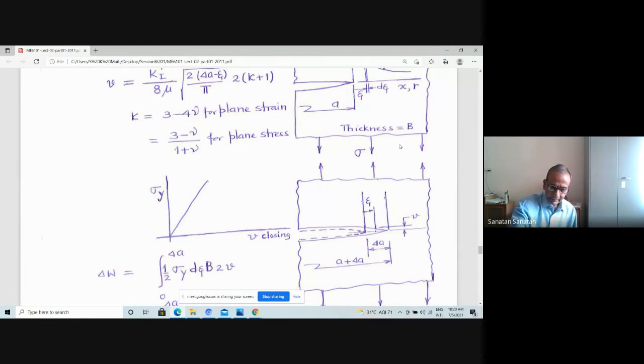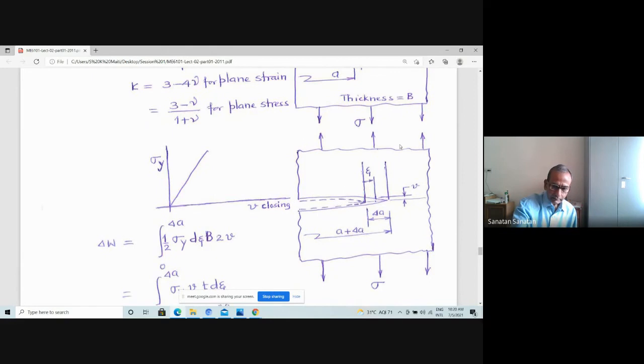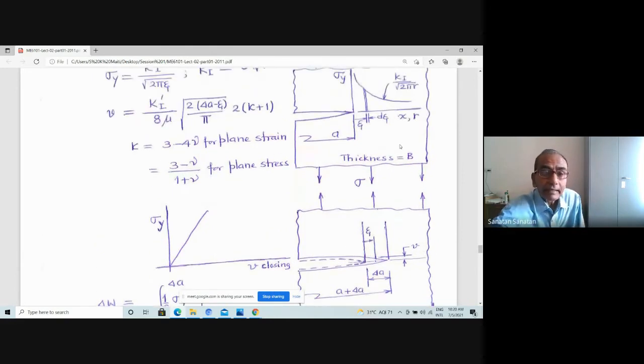Yeah, you see what I'm saying, that as the crack is getting load free, it is giving that much displacement. So at each point, some load is there, which depends on sigma y, and it becomes opened up by this much. So one can calculate that if you want to close the crack, we have to pull the two crack faces by loading sigma y on the crack faces, to put that displacement to 0. The work done in closing the crack is nothing but the energy which got released during extension from the original crack to the extended crack.